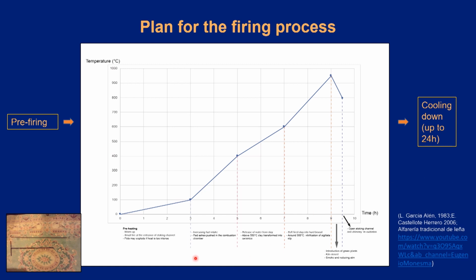From 100 to 400 centigrades, we will increase the fuel intake and push the red ashes in the combustion chamber using an ancient Greek T-shaped iron rod replica like this one. Between 400 to 550 degrees, the water contained in the chemical composition of clay will be released. After about 550 centigrades, clay is transformed into ceramic. After 550 centigrades, we can increase temperature in order to transform soft fired clay into hard biscuit.